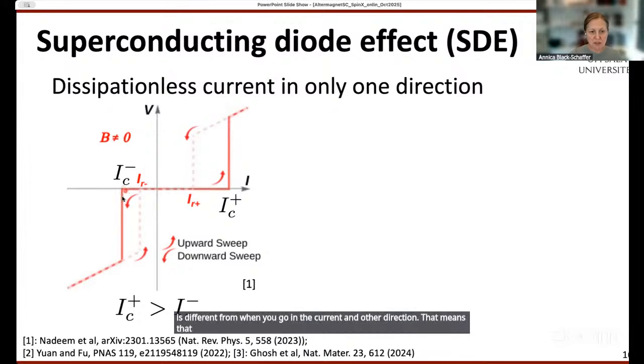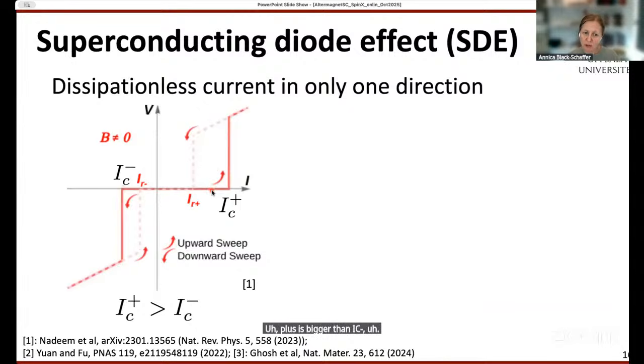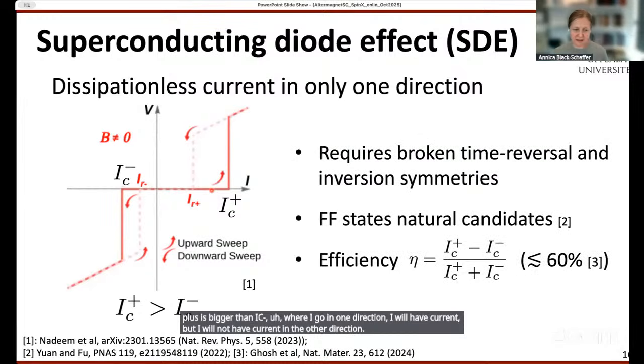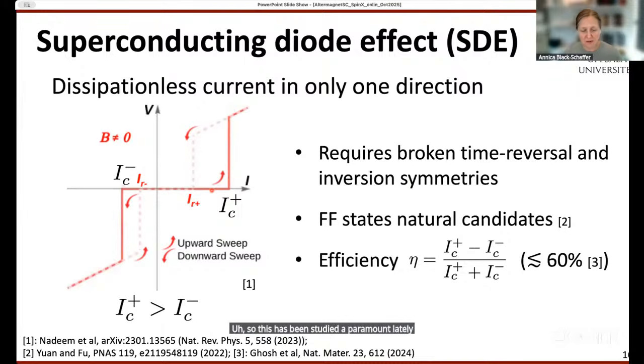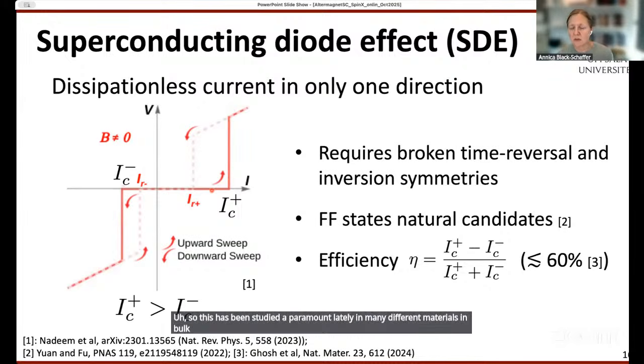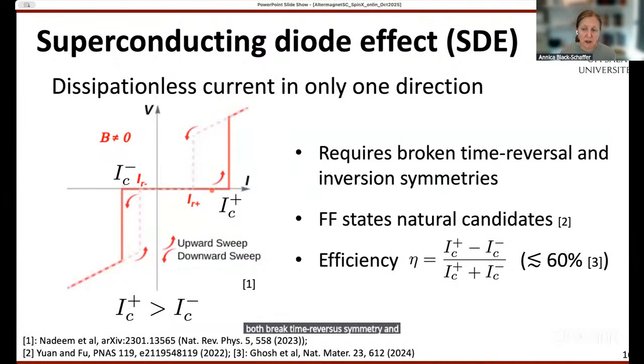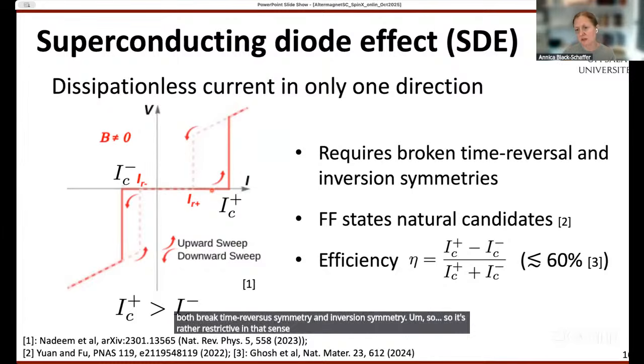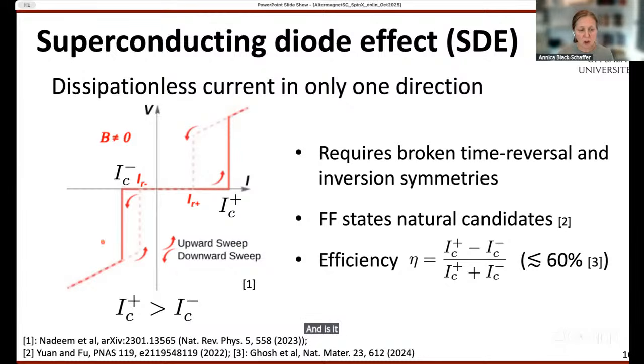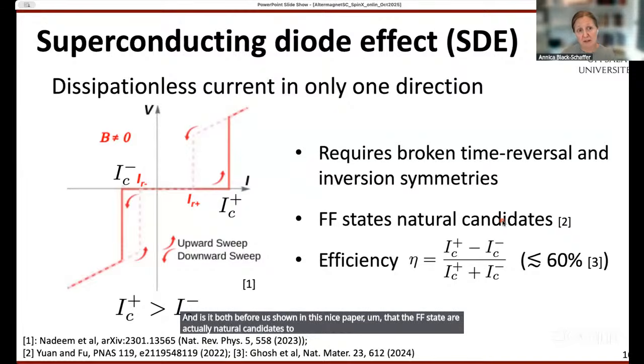That means that there is a regime when IC plus is bigger than IC minus, where I go in one direction, I will have current, but I will not have current in the other direction. So this has been studied a fair amount lately in many different materials, in bulk and in heterostructures and so on. And it requires that you break both time reversal symmetry and inversion symmetry. So it's rather restrictive in that sense, but there are many systems that still will have this. And if they are superconducting, you actually find the superconducting diode effect. It was shown in a nice paper that the FF states are actually natural candidates to have a superconducting diode effect.